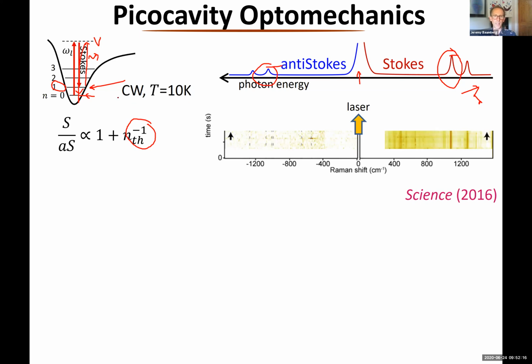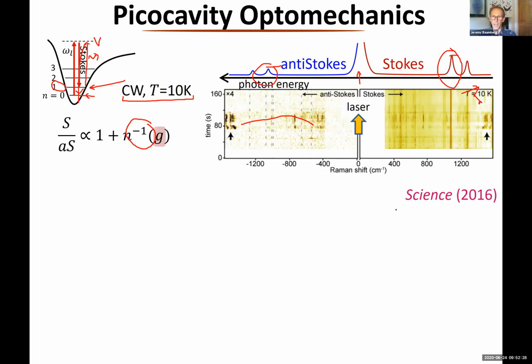Now I do this experiment in a nanoparticle on mirror. I cool this down to 10 Kelvin, which means that there's no occupation of this first excited state vibration. So indeed, I don't see anything here. But if I keep on watching, suddenly I see some amazing effects. I see extremely strong emission here, which is matched by emission here. If I were to calculate a temperature there, that would be thousands of degrees, more than the melting temperature of gold. So clearly something else is going on.